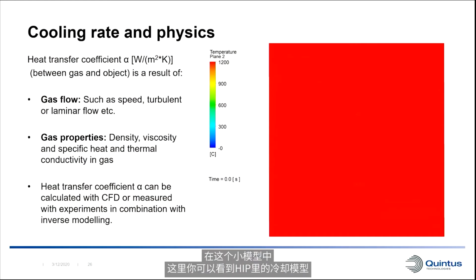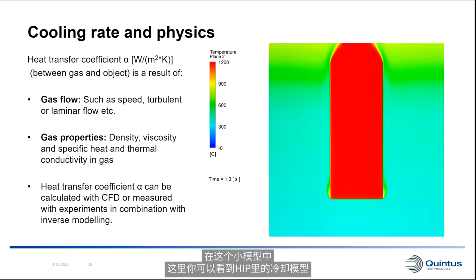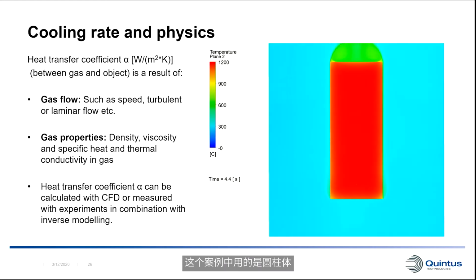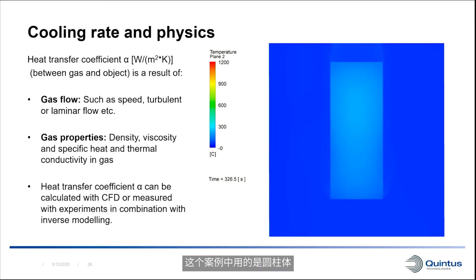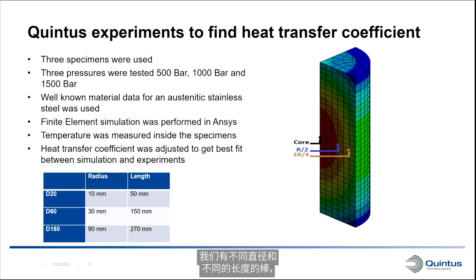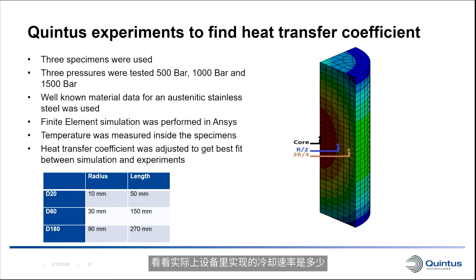In this little model here, you can see the modeling of the cooling in the HIP based on a cylinder in this particular case. And we can do this for any kind of part, really. In this experiment, we actually had bars of different diameter and different lengths. And we've had a thermocouple inside the material in the core, at half of the radius and at three quarters of the radius.